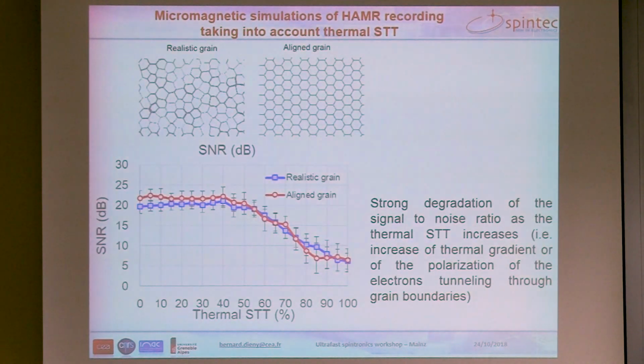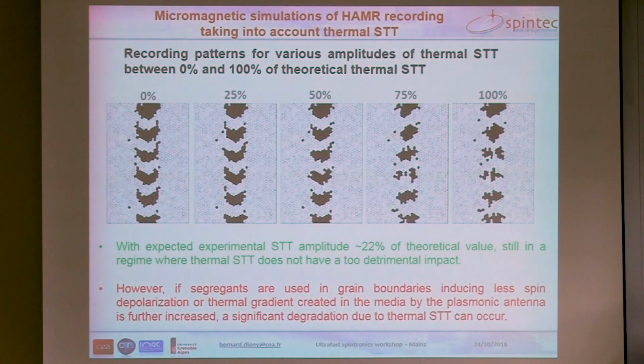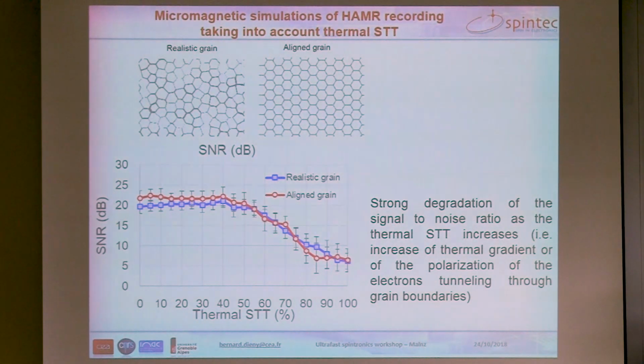We can even calculate the signal-to-noise ratio in this calculation, by analyzing the noise and the signal coming out of this media. We see that up to 50% of the thermal spin transfer torque amplitude that we calculated previously, we don't have much variation in the signal-to-noise ratio. And above, we have a strong degradation. Here we calculated for two kinds of media geometry: one in which we assume a distribution of grain shape and size, and another where we assume that everything is completely perfect. But you see there is little difference between the two situations.